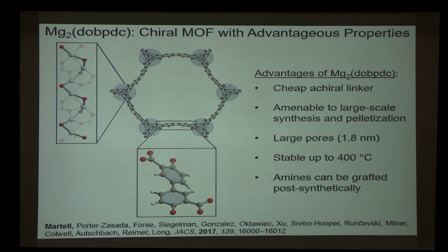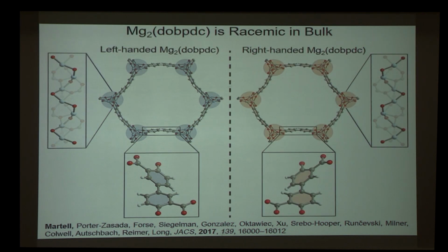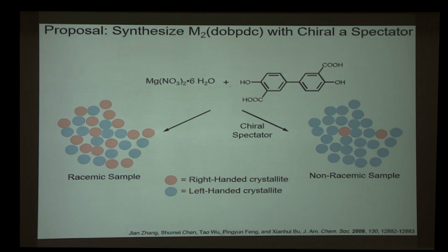So although this material was quite promising, there was a serious issue, which is that this material is actually racemic in bulk. It has an equal propensity to form a left-handed structure and a right-handed structure. And any material that is racemic in bulk will not be useful for a chiral separation. So this is the situation we have. We have these chiral building blocks, and we're making an equal amount of left and right-handed MOF. But what I hoped I could do is add a chiral spectator during the synthesis to bind to the framework in the early stages of its growth and induce it to grow preferentially as one enantiomer.